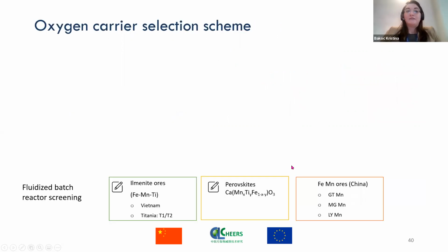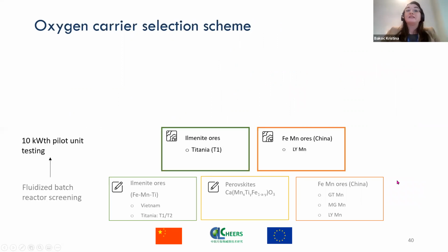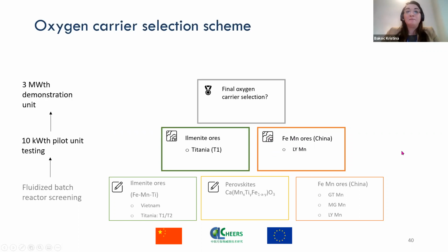So following the tests in fluidized batch reactors and the first screening, we have decided to perform additional tests in a 10 kilowatt pilot unit, which allows for continuous operation. As a representative of ilmenite ores, we chose Titania T1, since, as I have said, they have very similar performance between T1 and T2. And from iron manganese ores, we would test the LYMN, since the goal of this level of screening was to find the best possible candidate for the petcoke study. And of course, propose it for the operation in the 3 megawatt demonstration unit.